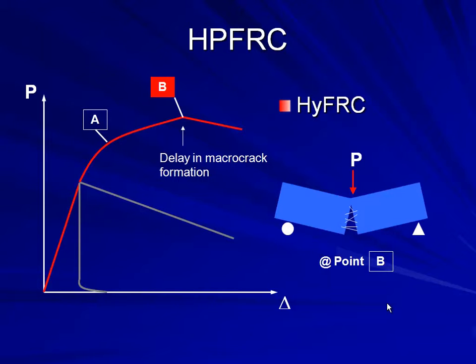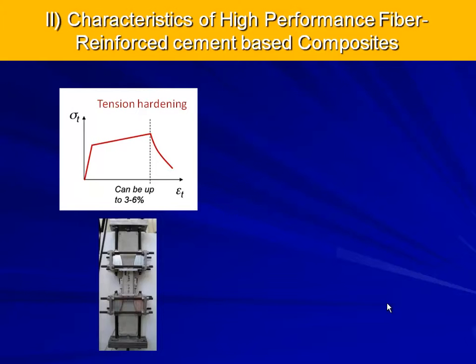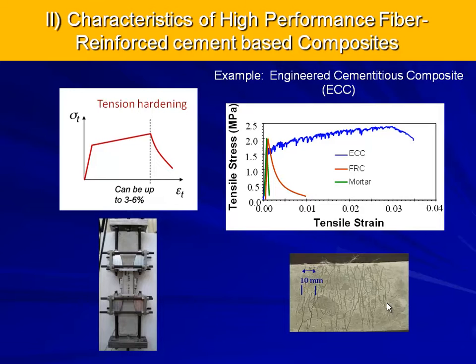What is the other characteristic? The other characteristic is in pure tension. When you do pure tension experiments, you have a tension hardening behavior. Here you have an example with the ECC, the engineered cementitious composites. Here you can see very clearly what happens to conventional fiber-reinforced: you have just purely the softening behavior, whereas for the high-performance fiber-reinforced, you see that strain hardening behavior right here. Your dominant crack only occurs at this point right here. This here is all associated with multiple cracking within the material.